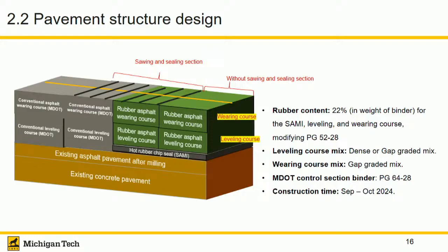All right, so what happened here is rubber asphalt on top, of course, to prevent the cracks from happening. We also pre-cut the asphalt portion on the top, according to the joints level. So anyway, that was something we tried. And also the rubber, well, before we put the rubber asphalt here, of course, we purchased a cheap regular binder. The asphalt we bought was PG 52-28, which was very cheap.